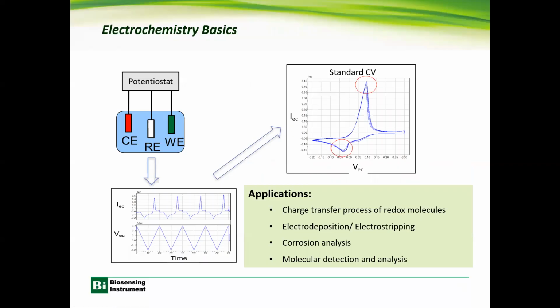And electrochemistry is actually quite a different technique. Electrochemistry is very powerful in controlling the process at a solid-liquid interface. So you basically have a solid electrode, a metal electrode. And by controlling the potential or controlling the current flowing to the electrode, you can actually control the reactions happening at the electrode surface, and therefore control the state, or the physical state, of the interface. With this technique, you can study things like charge transfer for redox reactions, electrodeposition, corrosion, and many others. So it's a very powerful technique.